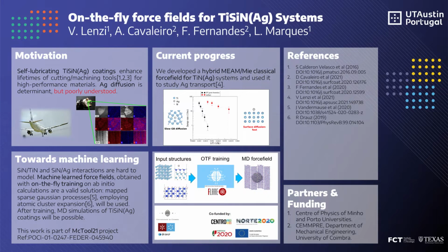We used it to run molecular dynamics simulations in order to evaluate the different possible diffusion mechanisms of silver within titanium nitride. And we found that, while the diffusion in bulk is prohibited and the diffusion along grain boundaries is very slow, the diffusion along surfaces, which happens in correspondence of the intergrain spaces, is the dominant process behind silver transport.